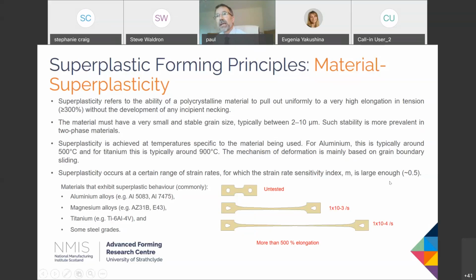So superplasticity, enhanced plasticity, we can get it in a reasonable range of materials, but we do need some fairly carefully controlled conditions in order to generate it. Some detail around that. For aluminium alloys, we will be forming them at around 500 degrees C or perhaps slightly more. For the titanium alloys, Ti64 is the main one, that forms at around 900 degrees C. And the little clip that you just saw there was of a big SPF press, and that was, as you saw, sort of orangey red. So that would have been around 900 degrees C.